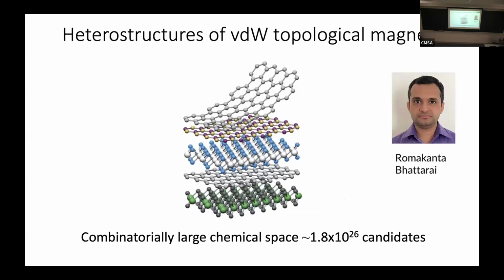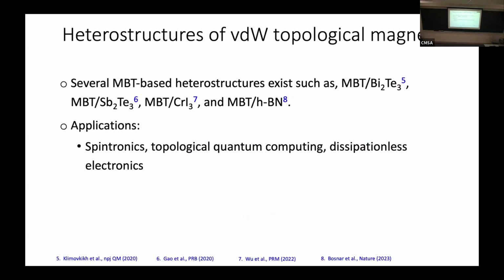So the combinatorial space becomes really enormous. In this case, I constrain my 2D materials to, I think, 1,000 or a couple thousand, which is not unreasonable, because before we found that you could be as high as 10,000 for a particular crystal structure type. And if you include maybe 3 or 4 layers, you get about 10^26 candidates, a really large chemical space of these 2D heterostructures. So having a tool like AI help us figure out where to focus our material search is invaluable.